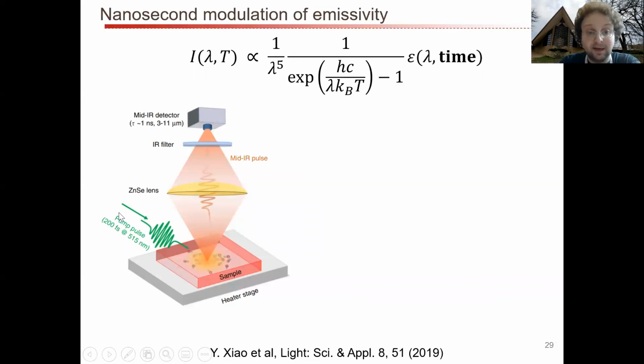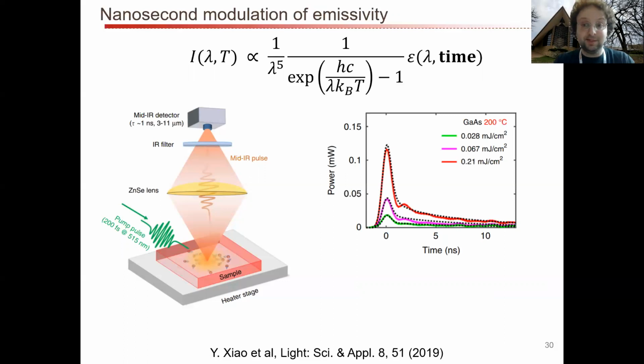We excited it with a pump pulse. This was done using some high-power lasers at the Naval Research Lab in the group of Alberto Piqué, our collaborators. This pump pulse temporarily excited a very large number of free carriers, which changed the emissivity dramatically. And for that short amount of time, this sample became quite emissive. So there was a thermal emitted pulse, and then those carriers recombined and went away, and the pulse was gone.